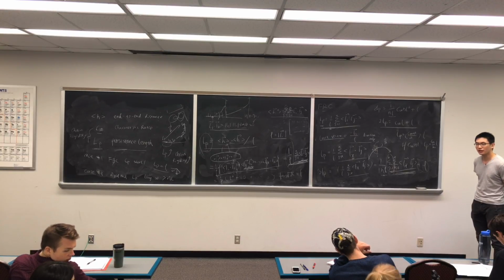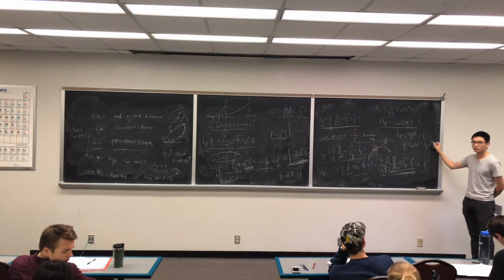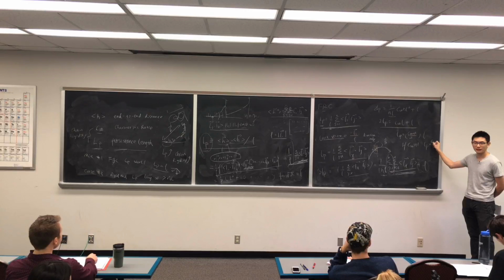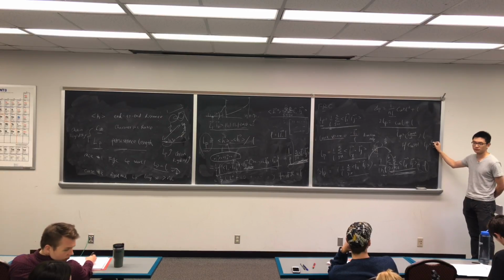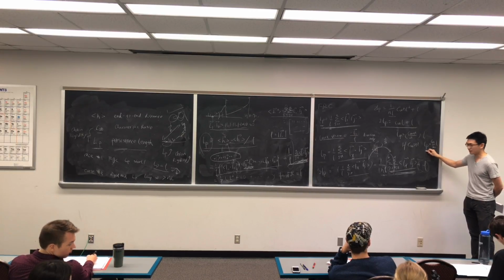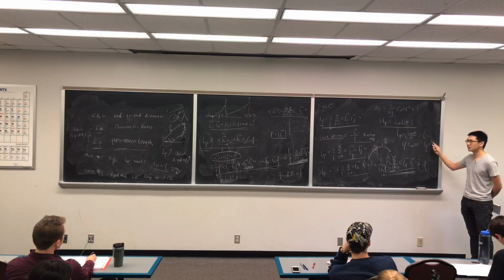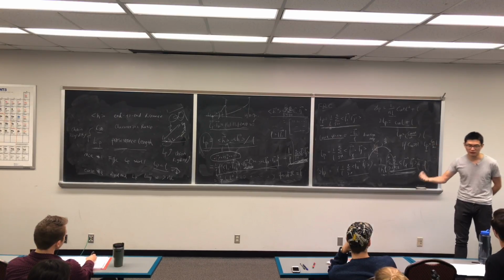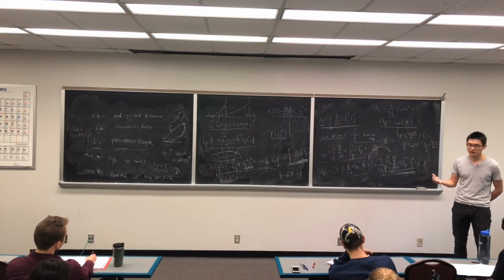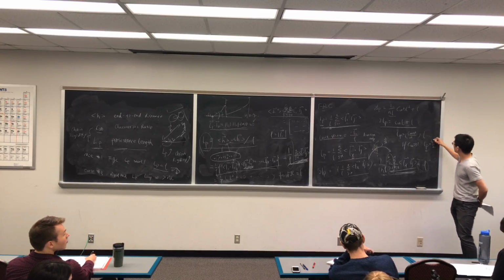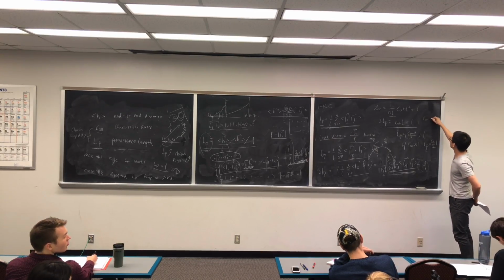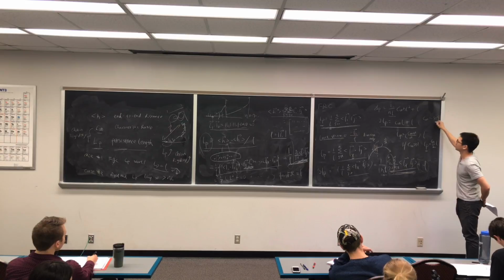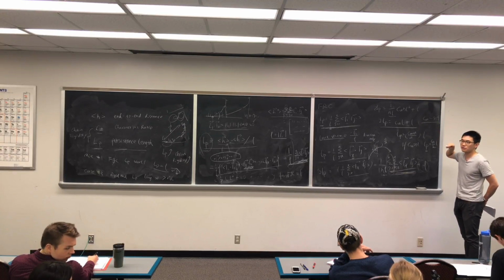So that's the connection between persistence length and the characteristic ratio. This is the length, but C is just a number, right? We talked about what C would be. C infinity is somewhere between 3 and 9. We chatted about this ratio.